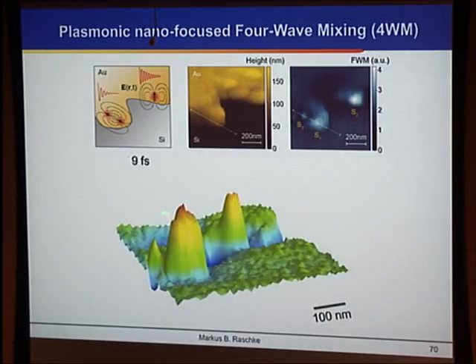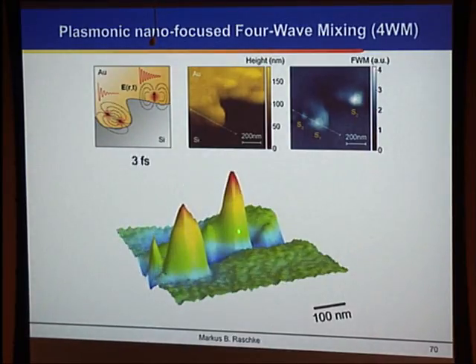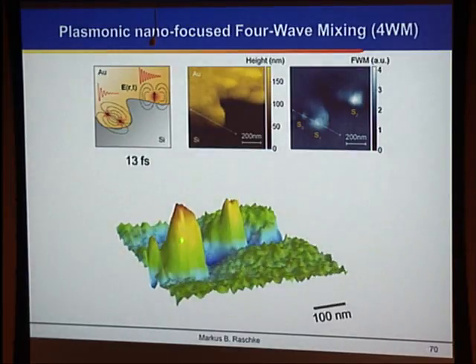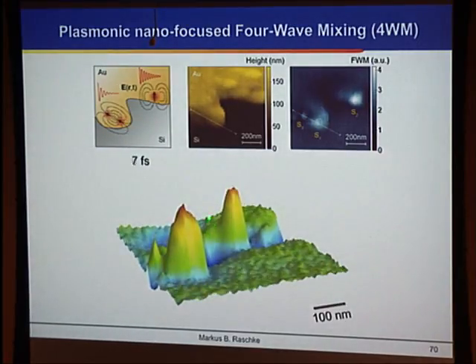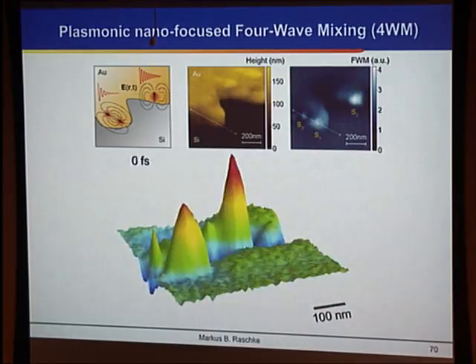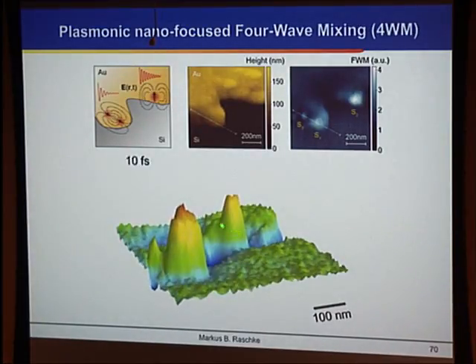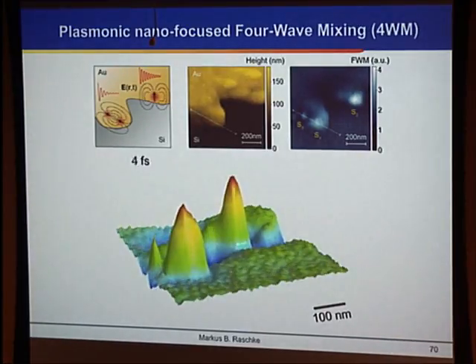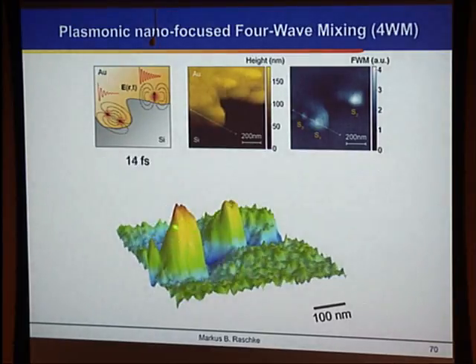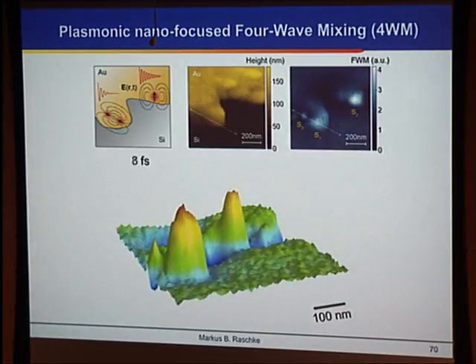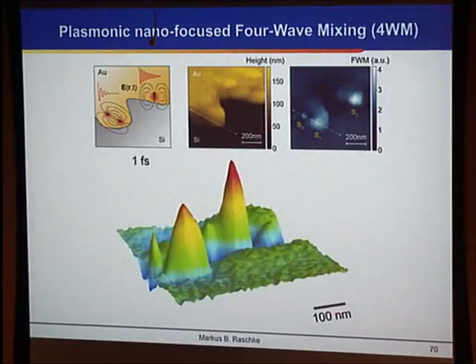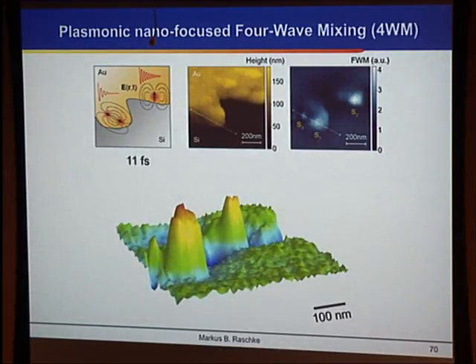And then you can really see that we see this decoherence of these coupled plasmons. You see a little emergence here back of a propagating mode responsible actually for the fact that these two are decaying slightly faster and transferring some spectral weight to the center one, which slows down this emission. So this is really the fastest movie.